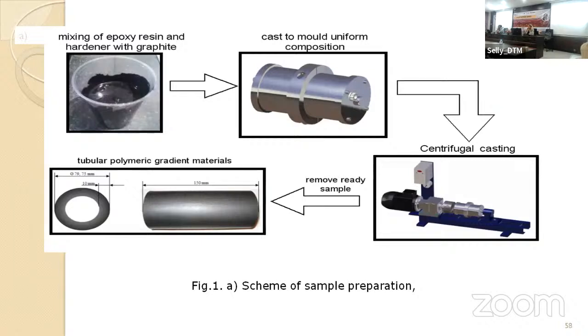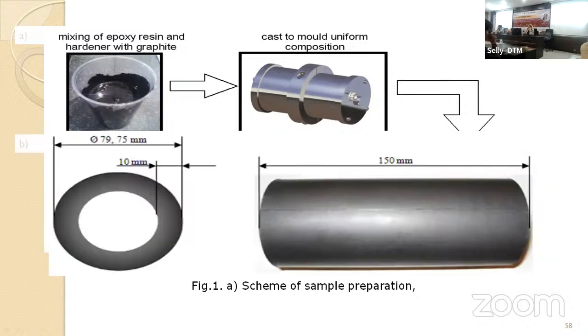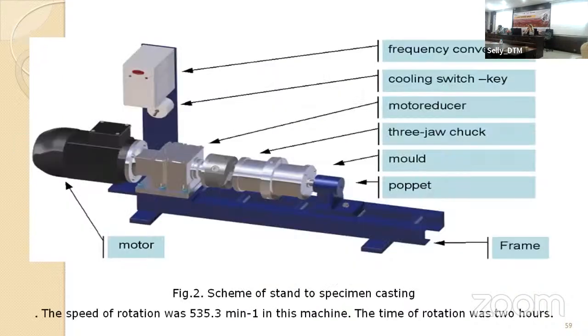Firstly, we mix the epoxy resin and hardener with the graphite. We have this centrifugal casting machine, and we remove the sample, which is a tubular polymeric gradient material. You can see its diameter. This rotation speed was chosen, and the time of rotation was nearly 2 hours.